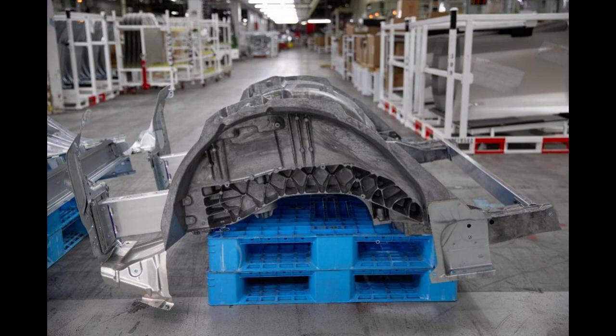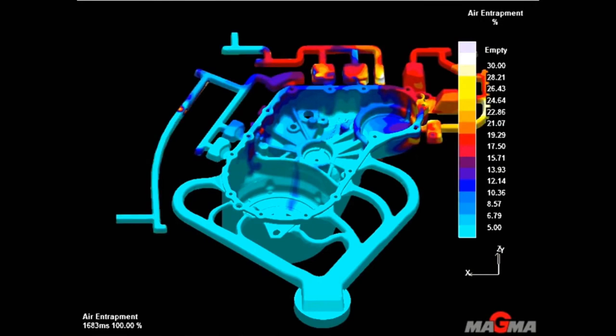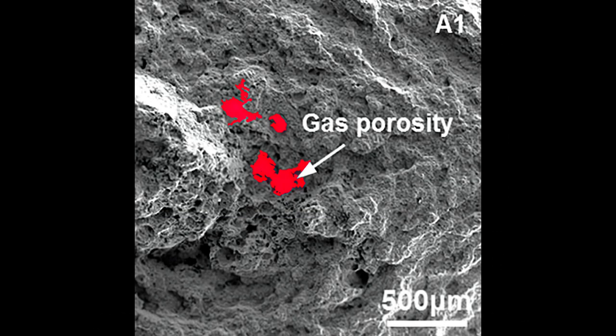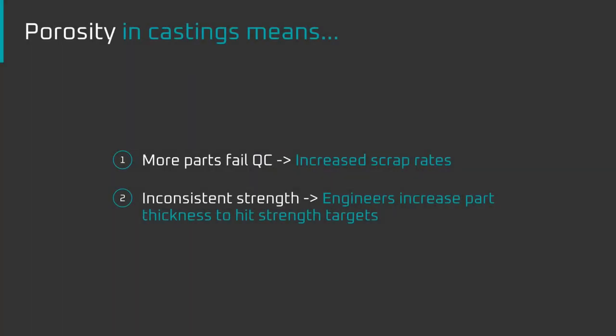This brings us to the first challenge of Gigacasting. The rapid injection of high pressure die-casting combined with rapid cooling causes air that's in the die cavity to become trapped in the cast part, creating porosity. Porosity weakens the die-cast part because where there should be solid metal, there's a void filled with air, which can lead to weak parts that crack easily. Furthermore, the porosity is random and therefore leads to inconsistent strength across castings. When part strength is inconsistent, there are two options: scrap the parts that aren't up to spec, and/or make the parts thicker and heavier so that fewer parts need to be scrapped. That is, porosity generates waste through scrap, extra mass through over-engineered parts, and heavy, inefficient vehicles.